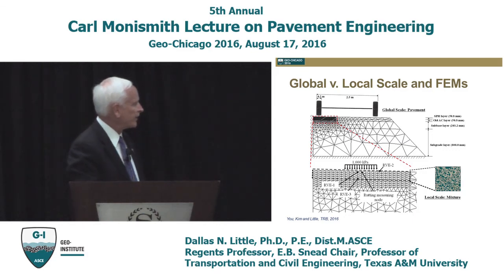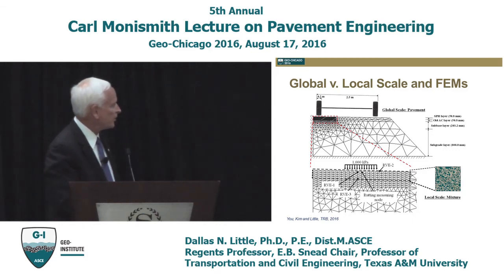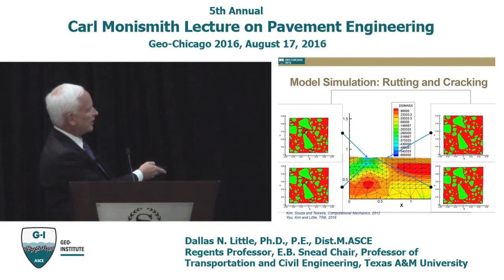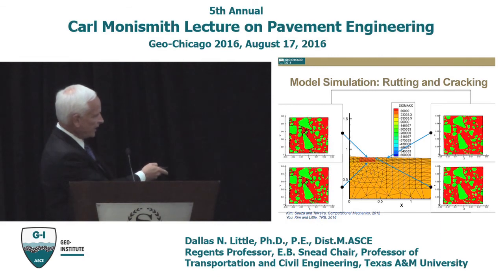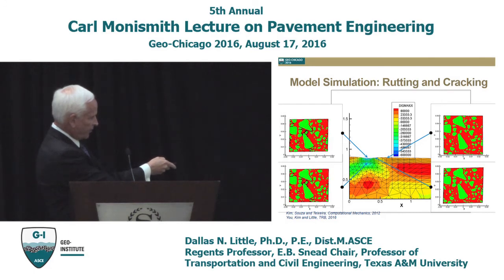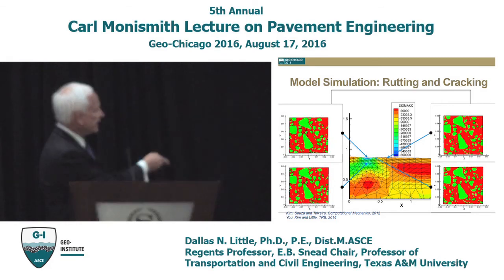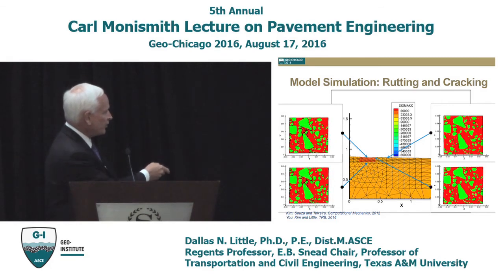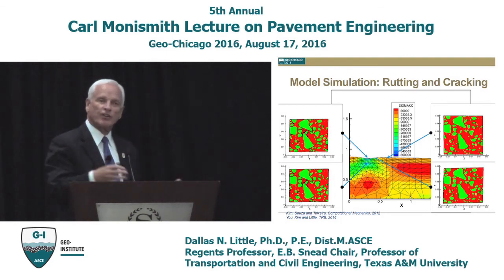So here's a little bit of an example, a little movie. I hope you can see it. We've got those elements that are located in different positions. One's right under the wheel, one's at the edge of the wheel, one's at the bottom of the AC layer, and one's way out here. And you can see the development of these damage areas that are developing into cracks, larger cracks.